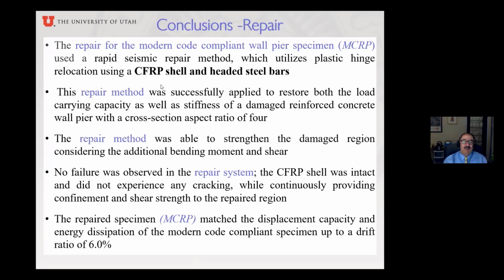We use what we call a plastic hinge relocation with that carbon fiber shell and the headed steel bars. This repair was applied successfully and restored both the load carrying capacity and the stiffness of the damaged reinforced concrete wall pier with a cross-section aspect ratio of 4. So the repair method was able to strengthen the damaged region considering the additional bending moment and shear.